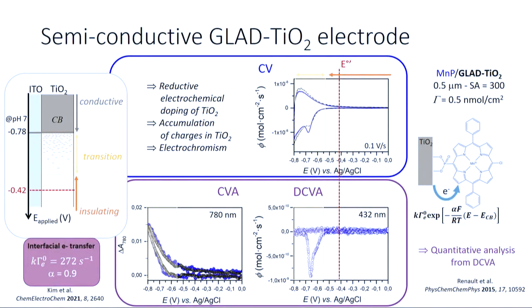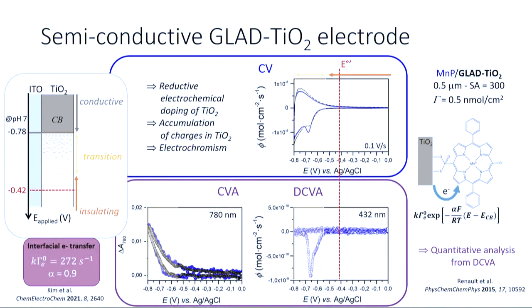But what's happening with titanium dioxide is that now, if you apply a reductive potential, you can electrochemically dope the material, and you start by filling some electronic traps in the band gap, and finally you reach the conduction band. And once you get the conduction band filled, then it behaves just like a metal-like electrode. So you have this reductive electrochemical doping of titanium dioxide, which is associated to an accumulation of charges, electron and protons in that case, in titanium dioxide, and it's also associated to an electrochromic property of the material that we can now follow around 800 nanometer, which is what you can see here. Okay? So this is the trace of electron-proton accumulation in titanium dioxide.